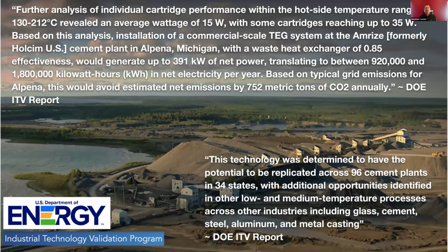So what was the output? We were able to run this test across a wide range of temperatures. As I said, we were all the way down to 130. Unfortunately, we didn't get up to the full 240 C. We were at 212 at the high end. But the average, and that average, as the DOE puts it, cuts off the top and low performers to develop that mean in the middle, ended up at a wattage of about 15 watts per cartridge, with some actually reaching 35 watts.